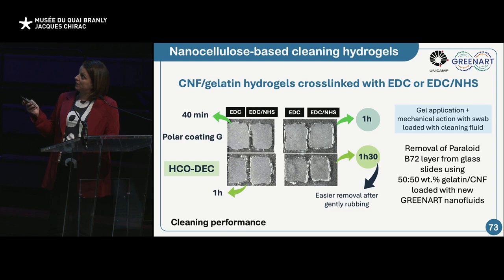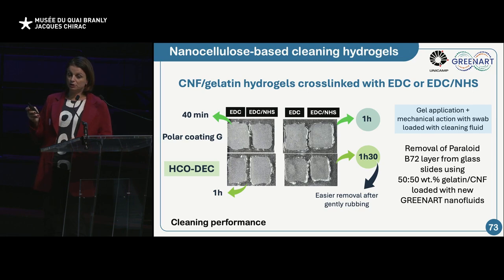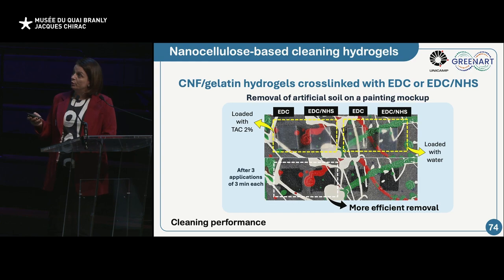Following the gel application, we used a swab to perform some mechanical action, but in all the cases we could remove the layer of Paraloid B72 that was on the glass slides using the gel. And the best system for us was the one using this new nanofluid after 1.5 hours. We also tested the CNF gelatin hydrogels on painting mock-ups.